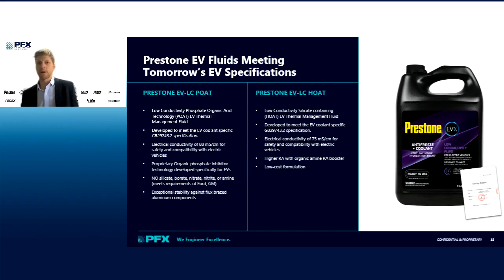And so Prestone's been working on this for a number of years. And we've developed 2 products to meet these specifications to fit different market needs. So the first product is a low conductivity phosphated OAT type coolant. This is less than 100 microsiemens. It comes in around 88. It meets all of the requirements for GB 29743.2, that Chinese specification. It utilizes proprietary organic phosphate inhibitor technology.